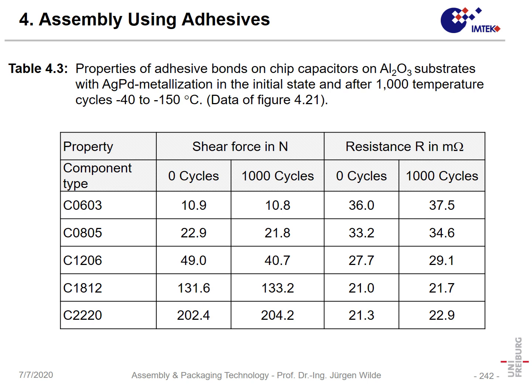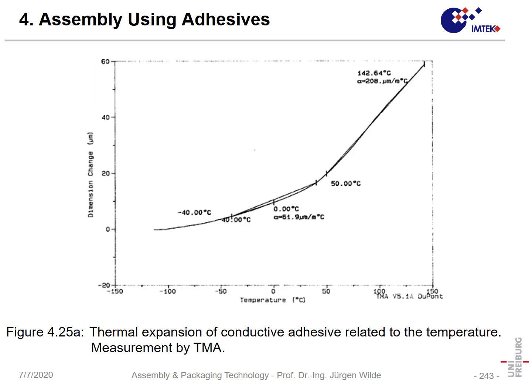Still, to give you some data about the shear force depending on that size, 10 Newton is roughly 1 kilo, and here 200 Newton is roughly 20 kilo. So these assemblies are quite strong. On the other hand, the resistance is also very limited, maybe in the 20 to 40 milliohm region, but it is not zero.